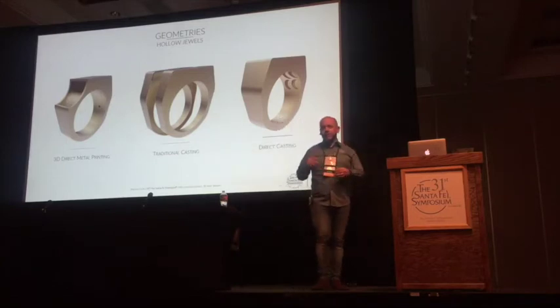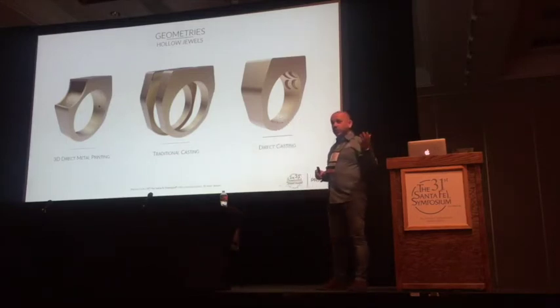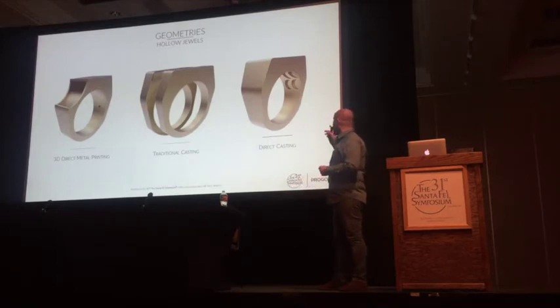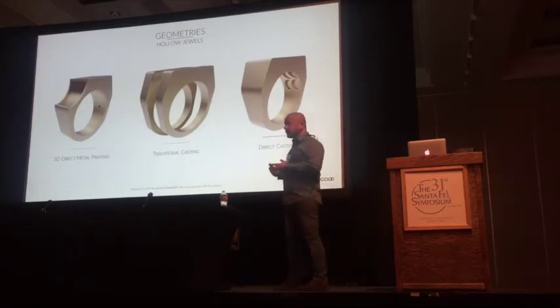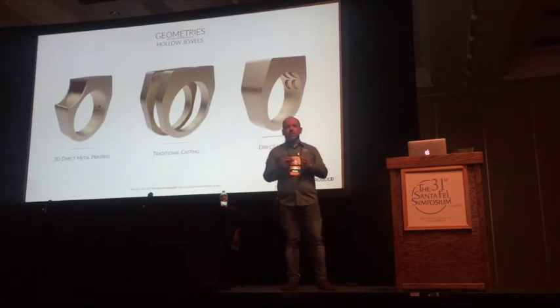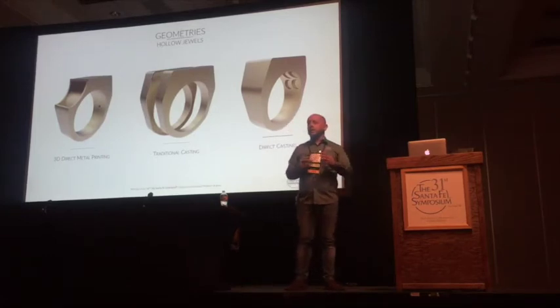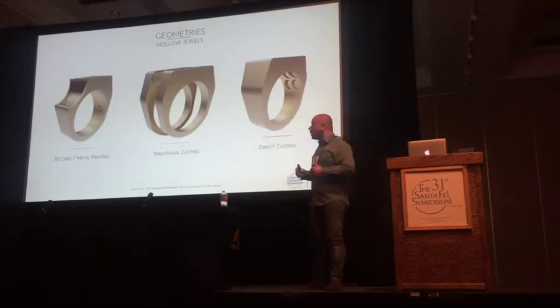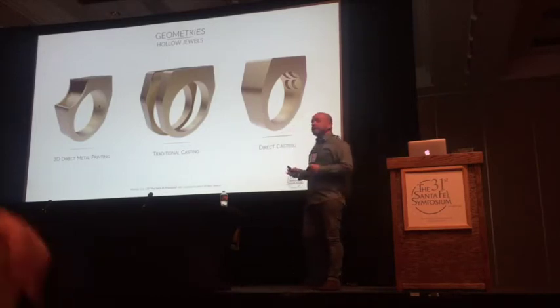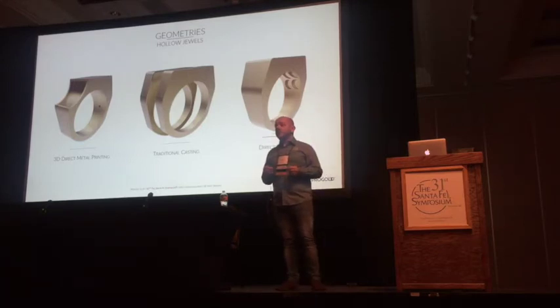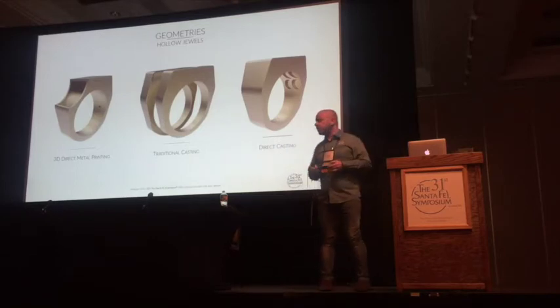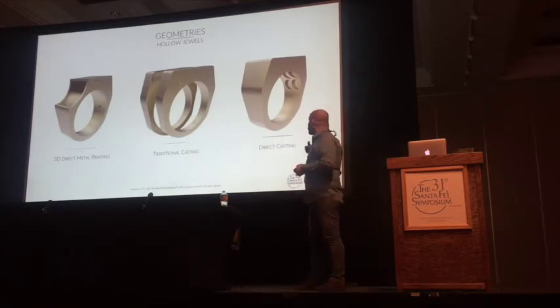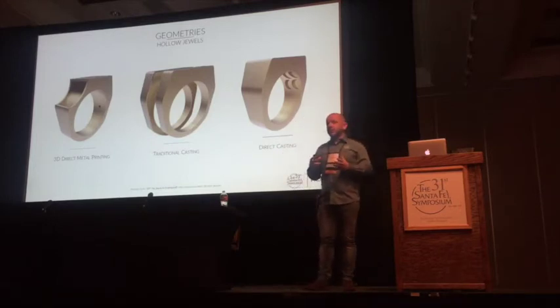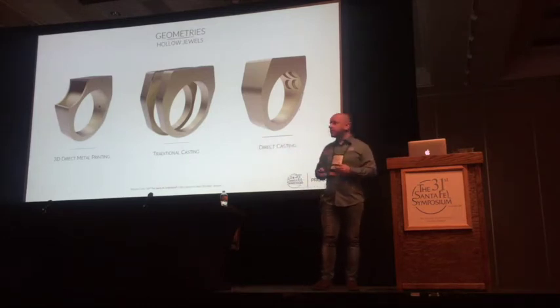That makes much more sense, because direct casting is something historical that is no longer used today. Anyway, in the case of direct casting, we have a pattern that is produced by a 3D printer in wax or resin, or traditional casting is something where you produce the pattern by injecting the wax into the rubber mold. In the case of direct casting, you can do a monolithic part, but you have to make some holes from where the investment is going in and going out after casting.